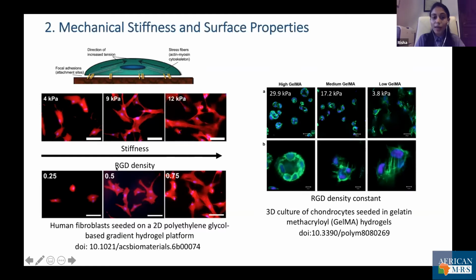The same applies to RGD density, that is the surface properties, which are modified by either chemically immobilizing these RGD sequences. RGD sequences are adhesive ligands, which will help adhesion of the cells. So as you increase the density, the cell spreading increases. So it can be either chemically immobilized or physically encapsulated.